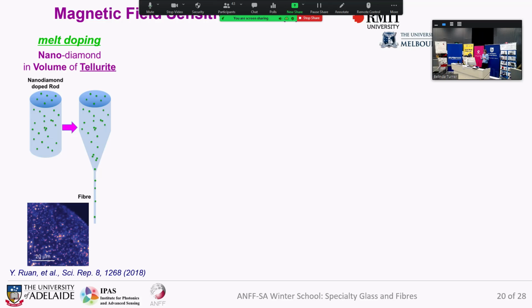It worked, and we could measure the magnetic field sensitivity, but it had two drawbacks. One was that tellurite glass is fragile, and because we exposed the diamond to a low viscosity glass, a large portion of the diamond particles didn't survive.